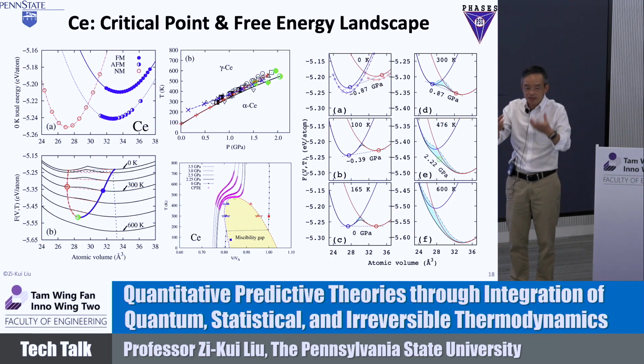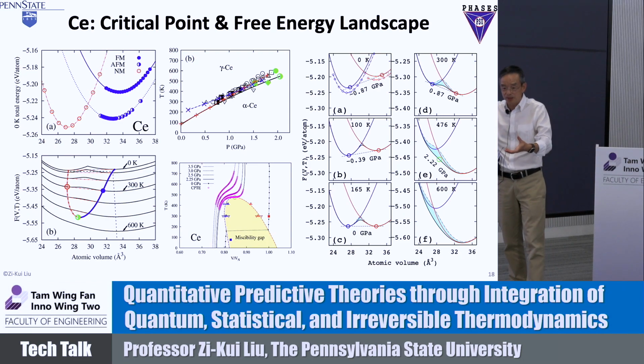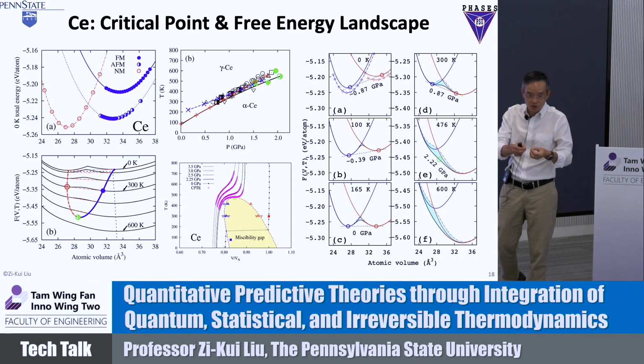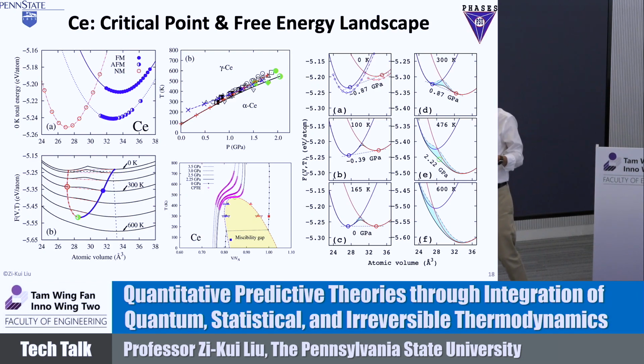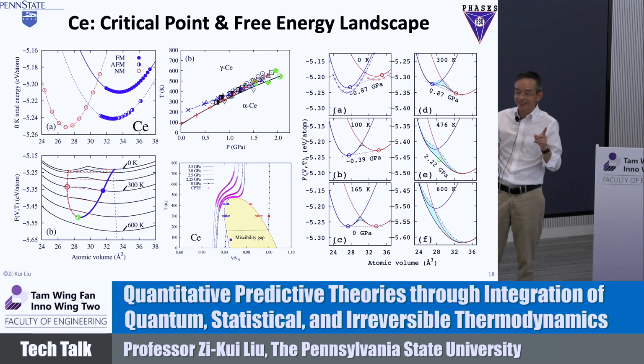The frustrated system has an instability, but the individual atoms, the individual bonding, has no instability. All the bonds themselves are perfectly stable. It turned out recently in experiment that if you measure locally, it's always stable. It's only when you put them together that it shows instability. Like a bird and a cage, it's the exact same thing. You have a bird and a cage that are always perfect, but you spin them too fast, you see the bird in the cage.